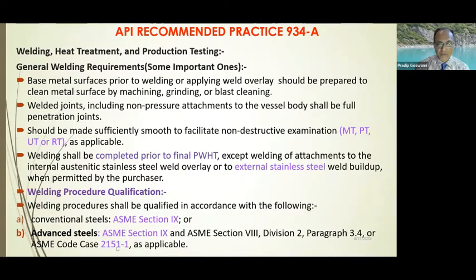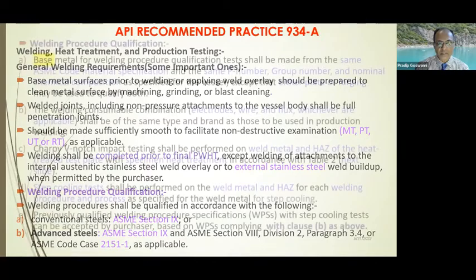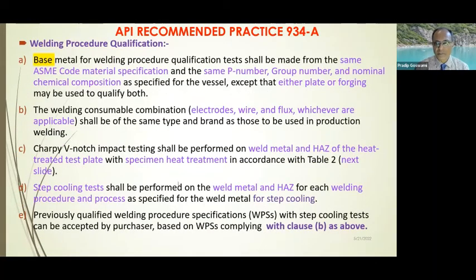3.4 or ASME Code Case 2151-1. These are very specific code cases which tell you exactly what the requirements are going to be, and one can find all these details if you just search on the net or on the respective ASME website. And as a matter of fact, during the procedure qualification, the basic requirement is that the base metal should have the same ASME material specification, same P number, group number, and nominal composition as specified for the vessel, except that this could be either plate or forging. You can use either shape for qualification of weld procedures.